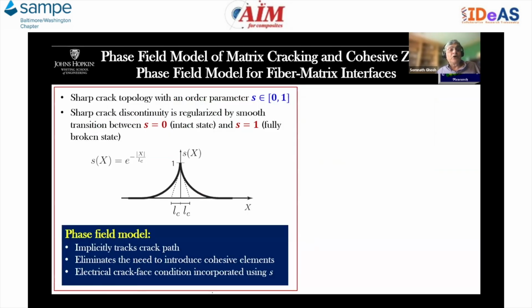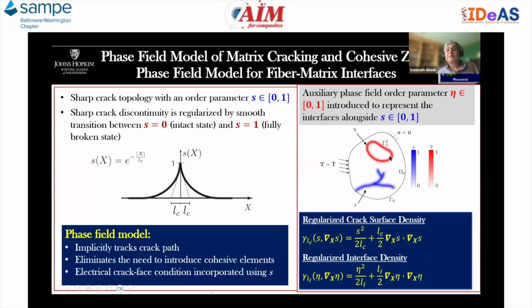We use a phase field model. A phase field model is a regularization of the sharp crack. And this is the regularization, as you can see. The advantage of the phase field model for modeling matrix cracking, as well as this cohesive zone-based phase field model of the fiber matrix interface, in the matrix, is that it implicitly tracks the crack path, eliminates the need to introduce cohesive elements in the general matrix, and the electrical crack face condition can be incorporated using the phase field order parameter.